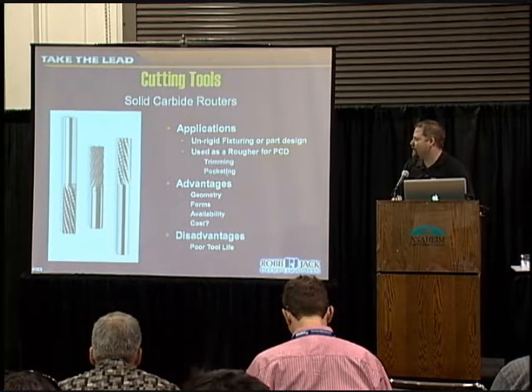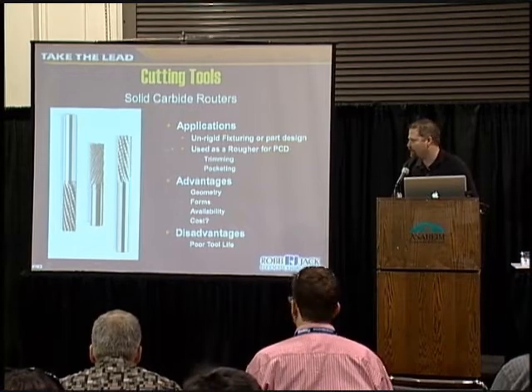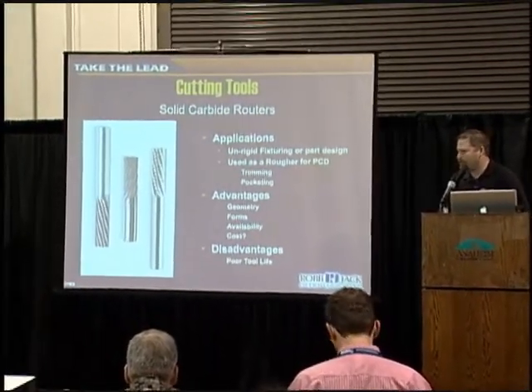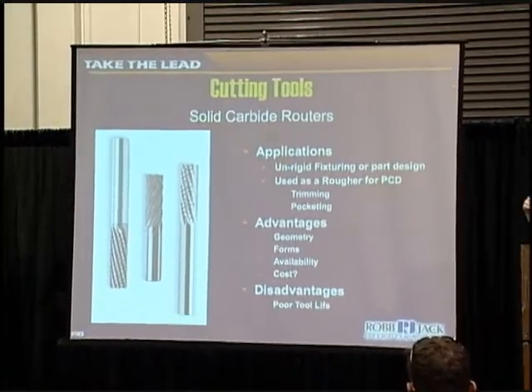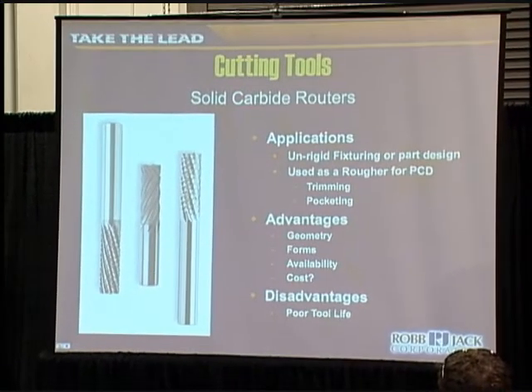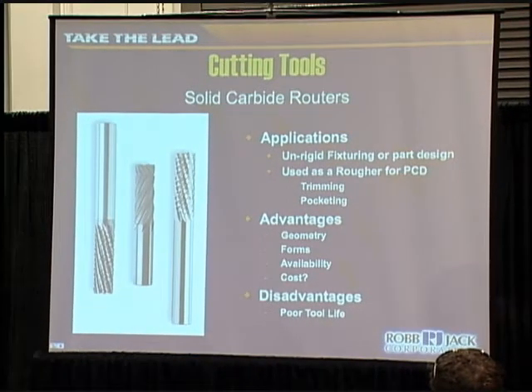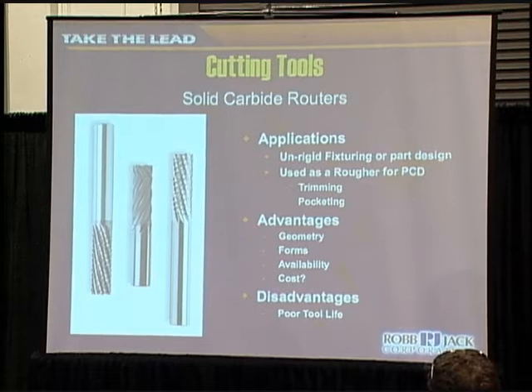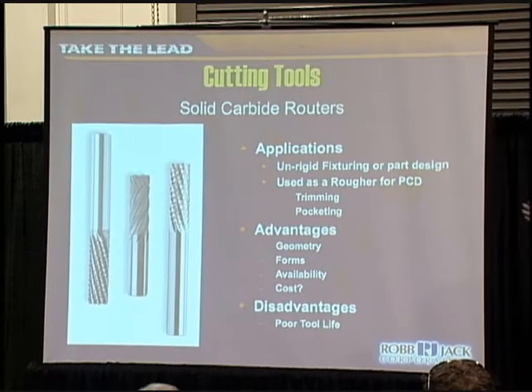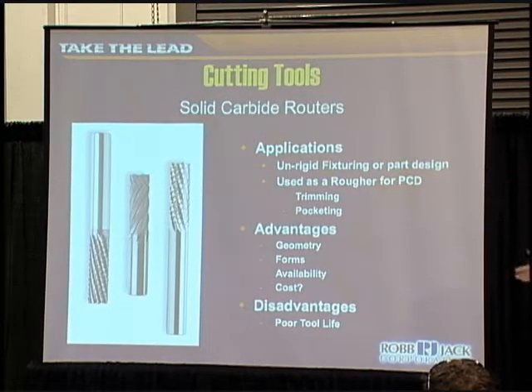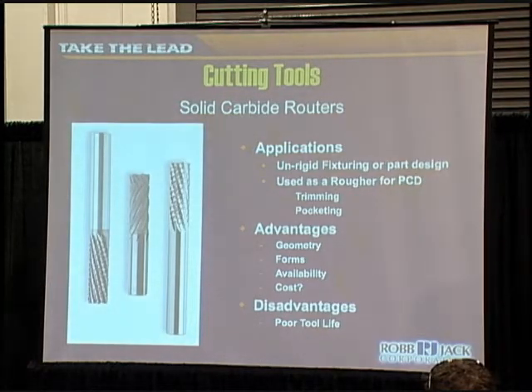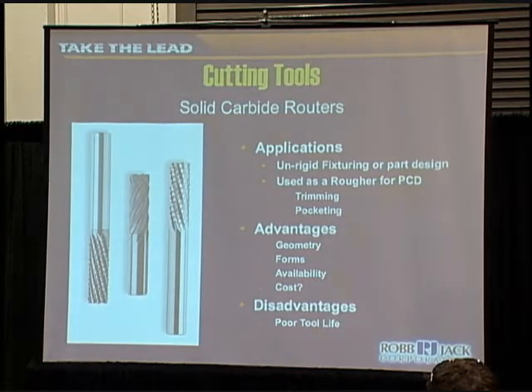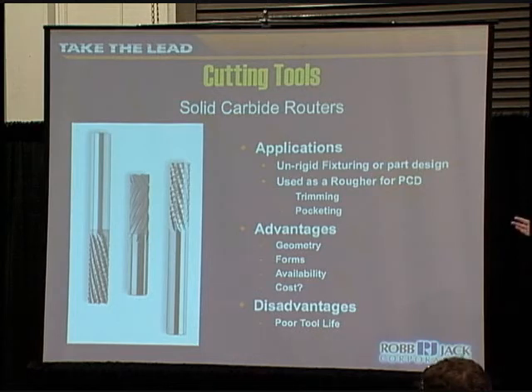The next style of tool would be a router. If you have very poor fixturing, your parts are vibrating, you can hear it cut, it's screaming, it's really loud, you probably don't want to go over to the PCD as your roughing tool. You may want to stick to the solid carbide router. The reason is it has better shock resistance, so you don't run into the chipping problems that you may with diamond. So as an alternative, you may want to rough out your parts with the carbide.